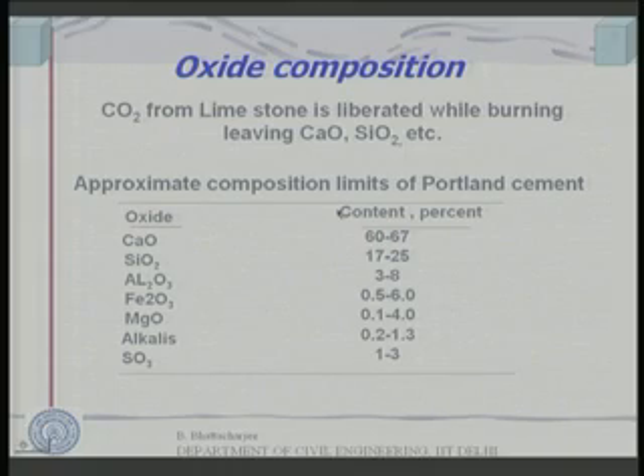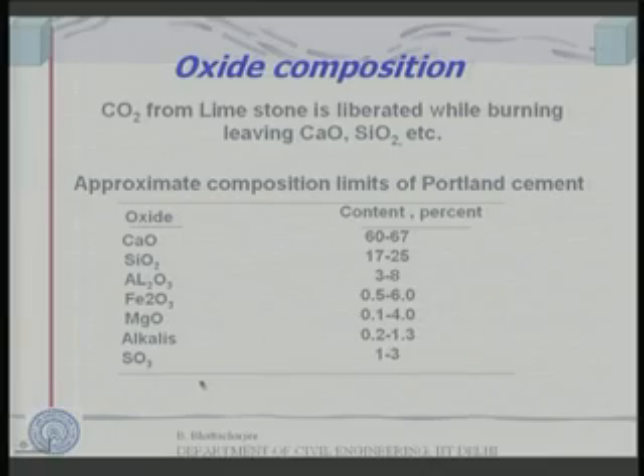Approximate composition limits of cement: calcium oxide in ordinary Portland cement is generally 60 to 67%, SiO2 around 17 to 25, aluminum oxide 3 to 8, and iron oxide 0.5 to 6%. Magnesium oxide is restricted to 0.1 to 4. There will be sodium oxide and potassium oxide alkalis, 0.2 to about 1.3, and sulfur trioxide 1 to 3%. There is also something called loss on ignition, which is a measure of unburnt material which can be burnt and formed into oxides. So, this is the typical oxide composition in cement.